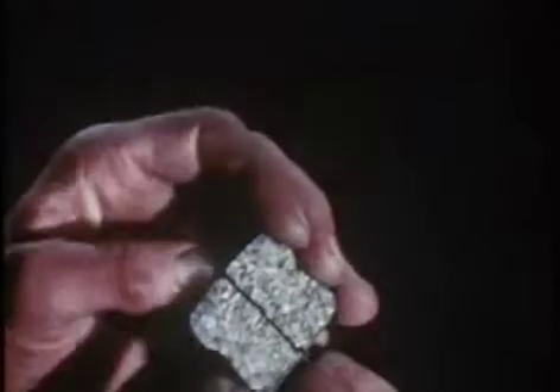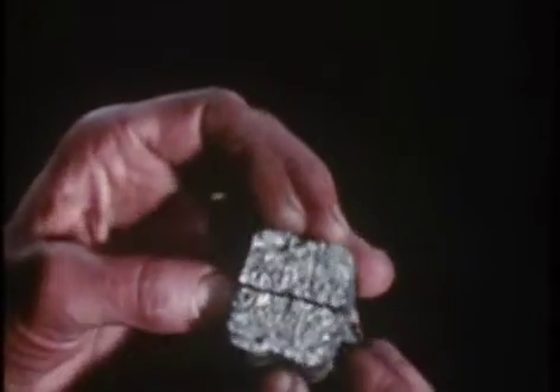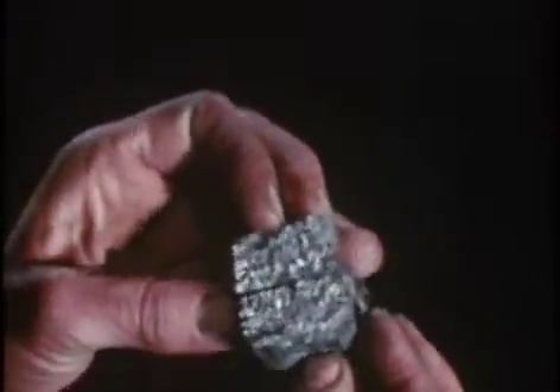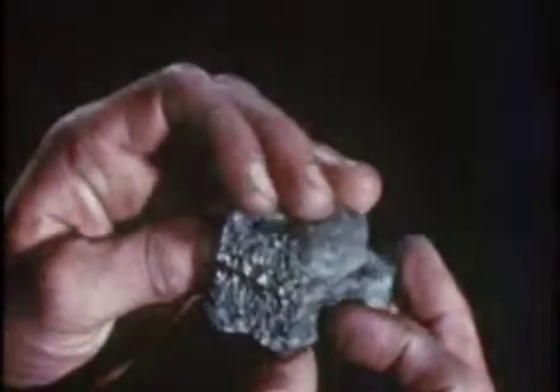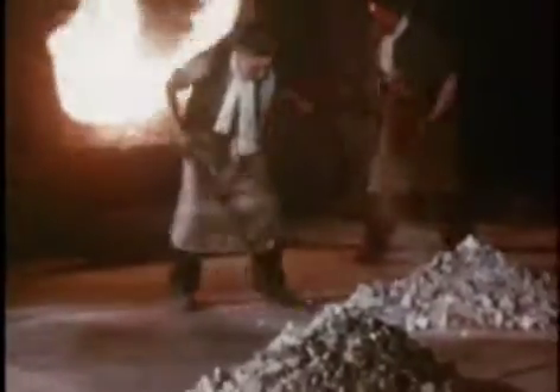A more rapid check of the general condition of the molten steel is obtained by expert examination of the crystalline structure of a fractured sample. The second slag for the reducing period is made by additions of lime and ground carbon for the removal of sulfur and oxygen.